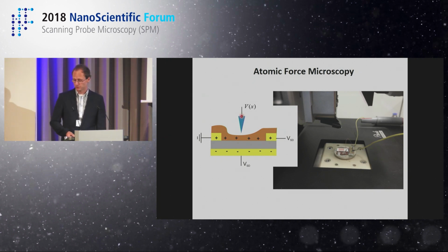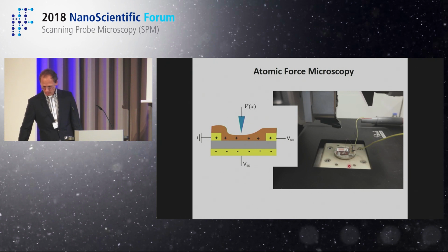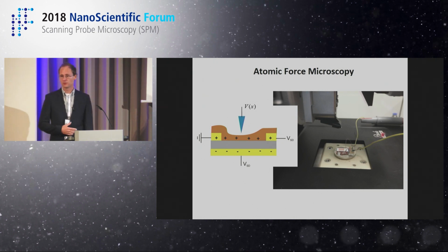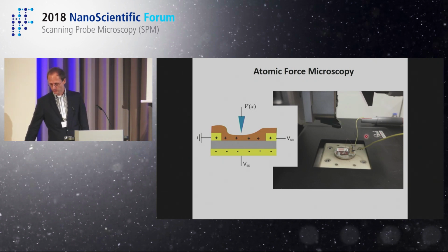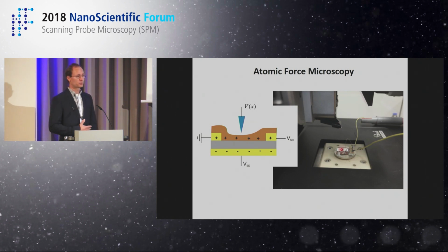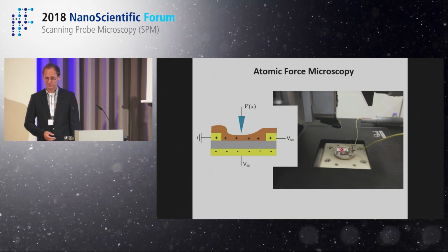So here's a gold-coated AFM tip. With the AFM, you can easily wire your transistor, as you see here. You can measure all the characteristics that you need. You can polarize it as you want, and at the same time, you can approach with your AFM tip and do all kinds of different experiments. Now, the question is, of course, which kind of electrostatic forces emerge in such an experiment, and there we have